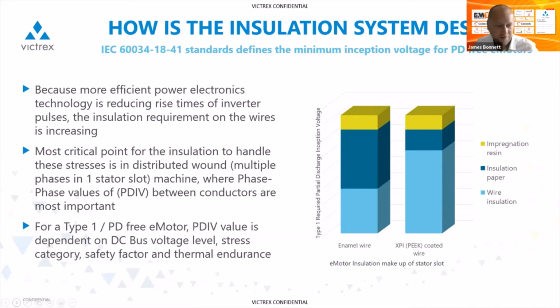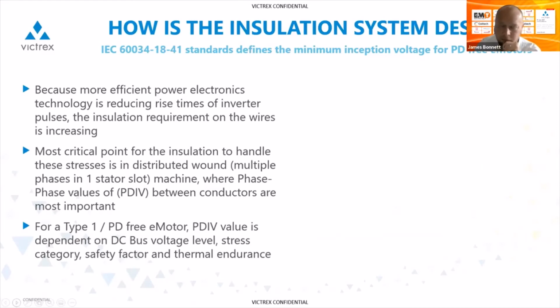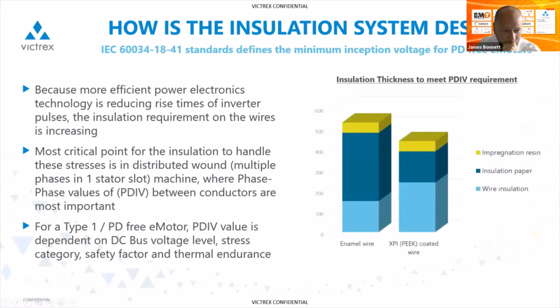So as you can see in the first graph, the XPI coating is contributing proportionally much more than the enamel. But you can see if I flick forward to the second graph, there is a thickness saving here in those overall materials, and that's what enables the increase in copper density that is ultimately one of the main contributors to the benefits that are laid out later in the presentation.